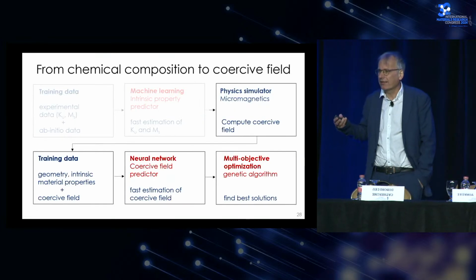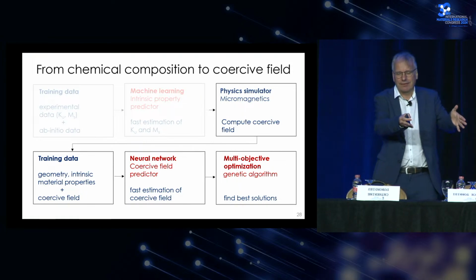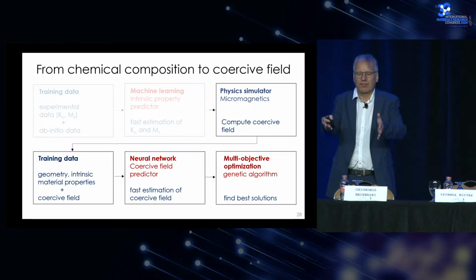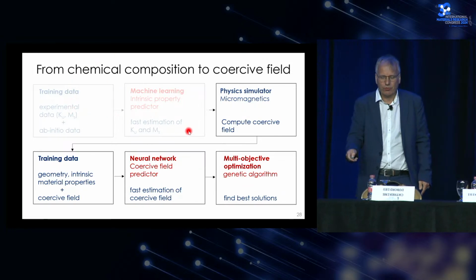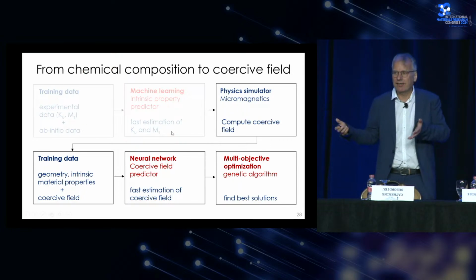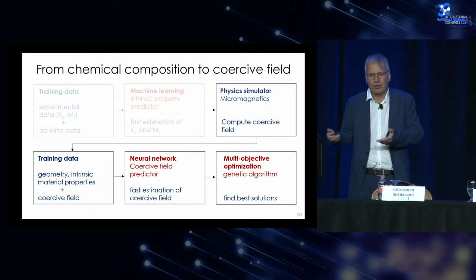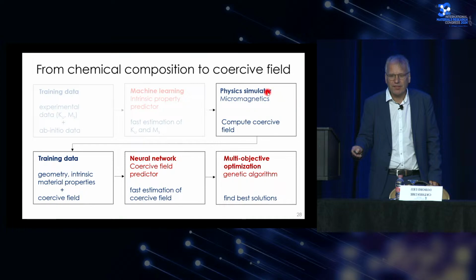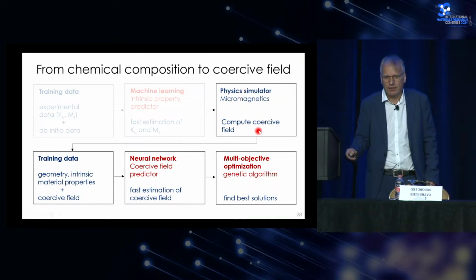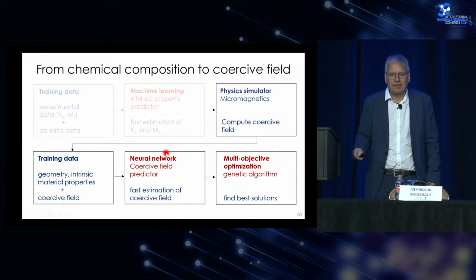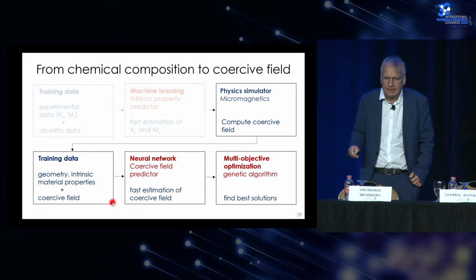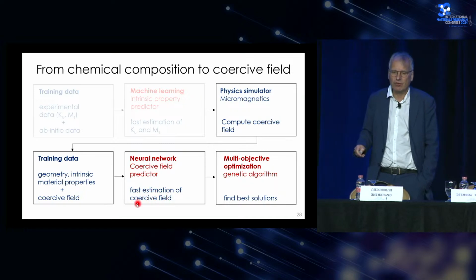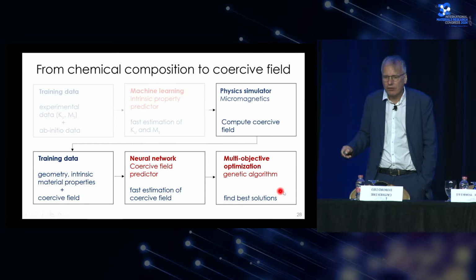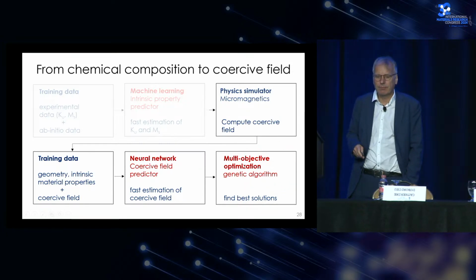Now we have to bridge the length scales. So we have the length scale of the unit cell, the chemical composition, towards the intrinsic magnetic properties, so shown by these two boxes here. And then we have the length scales of the granular structure of the magnetic material. So we now have our physics simulator that computes the coercive field. We do a lot of simulations. We generate training data. This training data is used for a neural network predictor of the coercive field. This neural network gives us a very quick estimation of the coercive field, and because it's so fast, we can use it in a genetic algorithm to find the best solution.